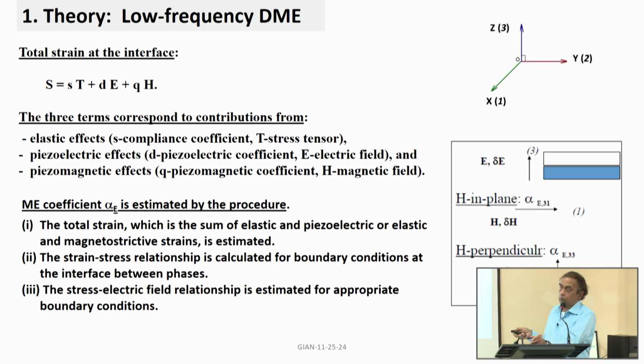So, how do you calculate the voltage coefficient? The basic equation is for the strain at the interface, the interface between the ferromagnet and the ferroelectric phase. That is given by this equation. The first term is the elastic effect, where T is the stress tensor times the compliance coefficient. Compliance is the inverse of Young's modulus. The second term is the piezoelectric effect, that is D times E. The third term is the piezomagnetic effect, that is Q times H.